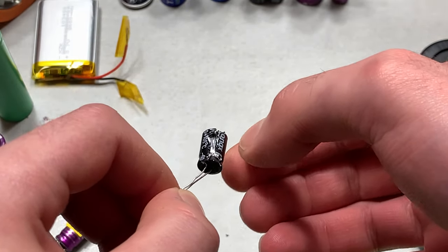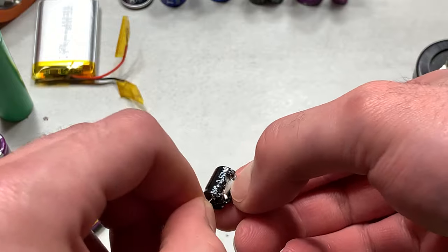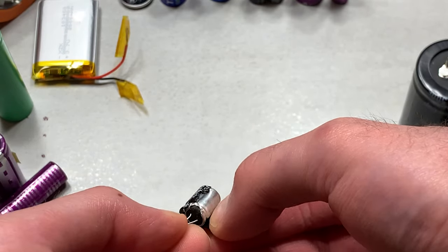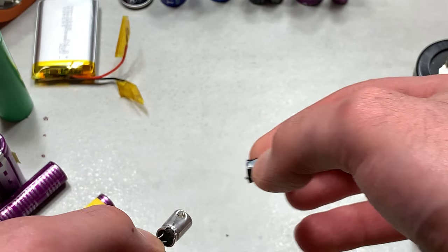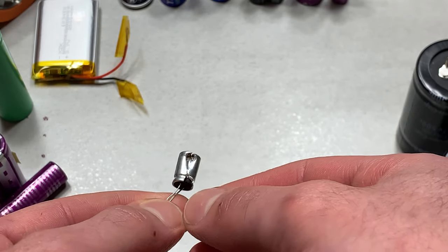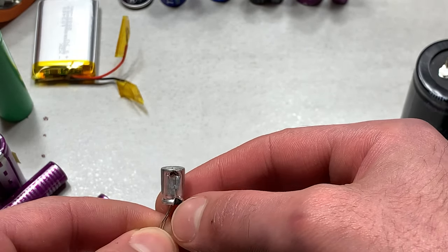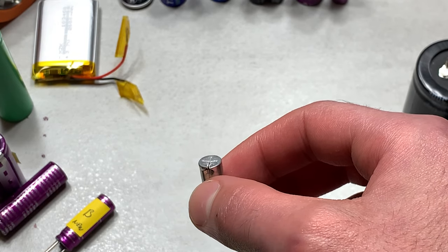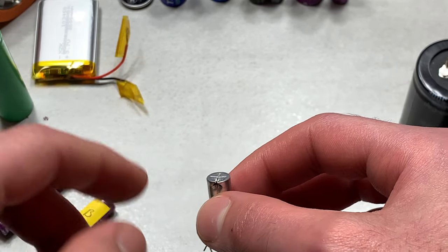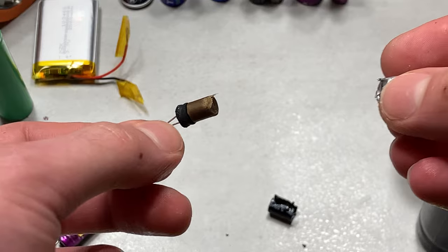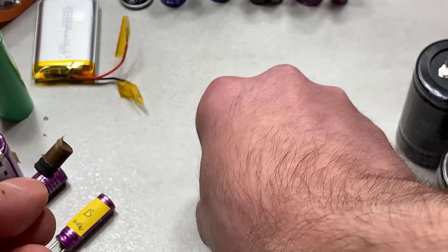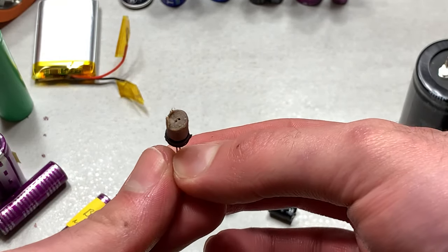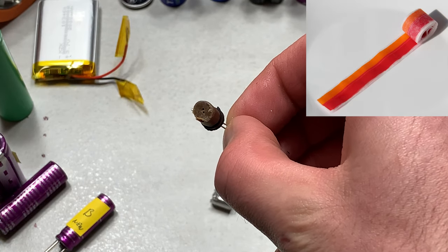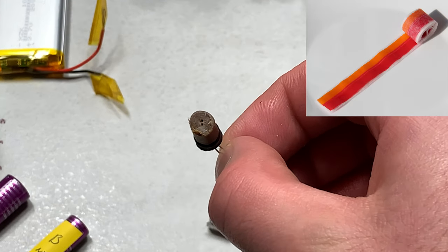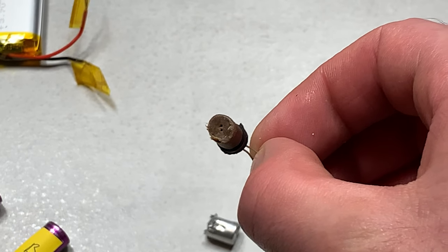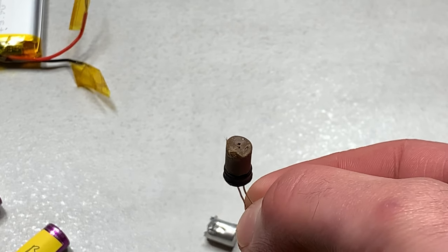Okay, so I've got it open here. I'm going to try to not touch the inside as much as possible. But essentially, we can see the aluminum coating with the top being scored so that if it does blow open, it vents in the top. Okay, so I managed to just pull the cap off, and this is where we can see the damp paper and where we can see it's sort of like the fruit by the foot roll I was talking about. So I managed not to touch the paper at all when taking this apart.